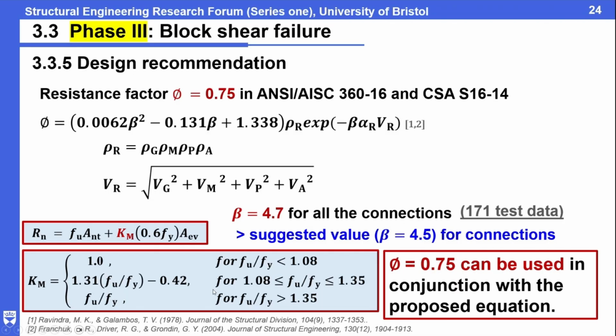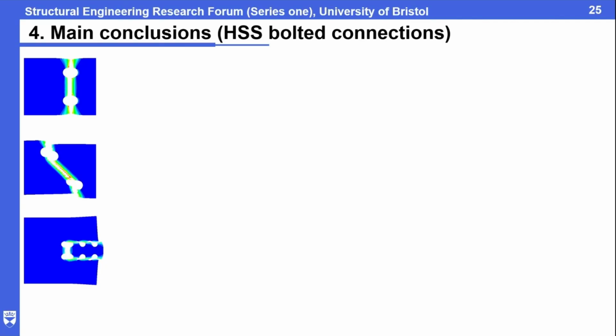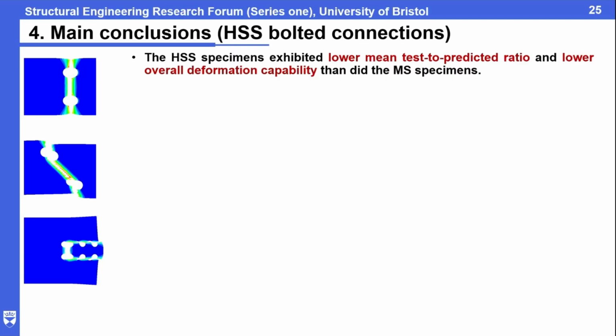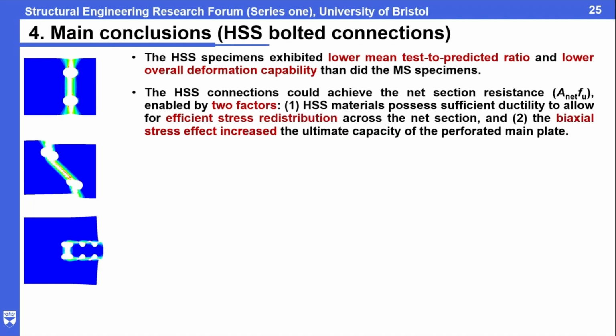So this is phase 3. Then we can go to the main conclusion for the high strength steel bolted connection. For the bolted connection ductility behavior, we compared the displacement at ultimate state. A lower ductility exhibits a lower test-to-predict ratio in general. And for the high strength steel connection, why can they still achieve the net section resistance although the ductility is lower? We found these 2 factors behind it: one is efficient stress redistribution, another is the biaxial stress effect.